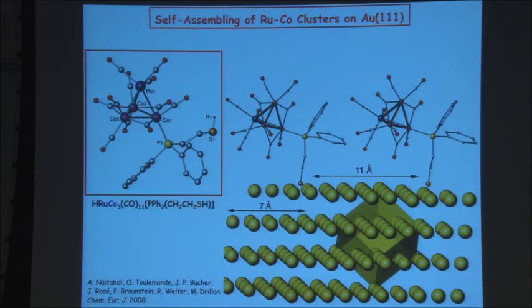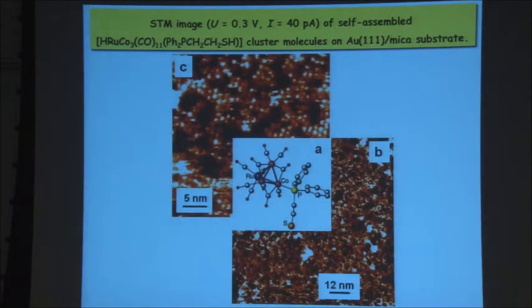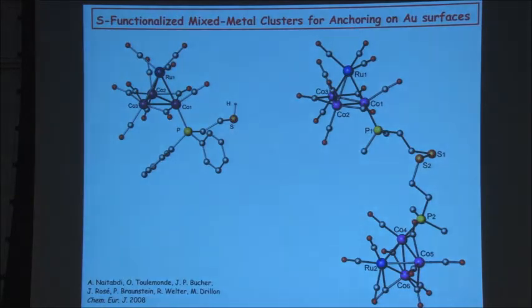This tetrahedral cluster, now we decorated with the thiol function, of course, to deposit them on the gold surface. Thiol functions like gold very much. So we had here this possibility to arrange these molecular clusters on gold 111 faces and try to look at the self-assembly. And then you can do a similar trick with the ruthenium cobalt clusters where you have the SH functionality here on the surface. So you can actually apply the concept to various systems.